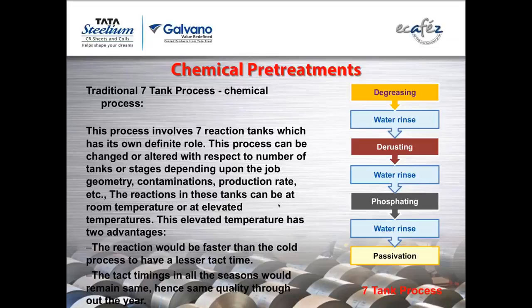Now I'll just explain a little bit about the 7-tank picture which you see on the right. The first stage is normally degreasing, where we are removing all the grease and oil. Along with that, whatever debris, whatever dust particles are sticking to that metal will get removed. These are mainly alkaline tanks. Alkalis react with the oils. Oils are long chain fatty acids, so alkalis are better to react with them. The reaction is called saponification.